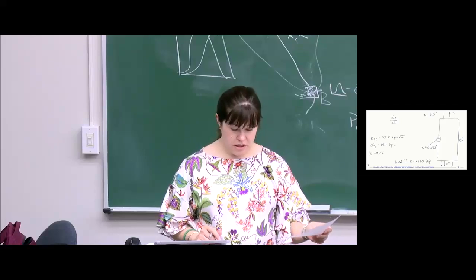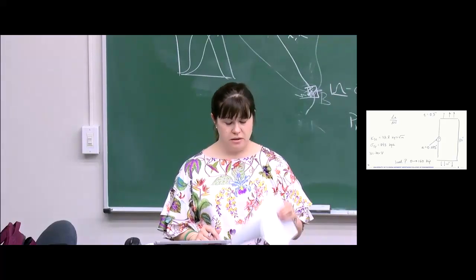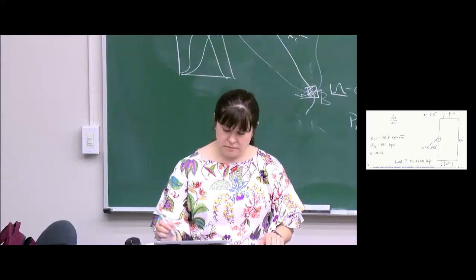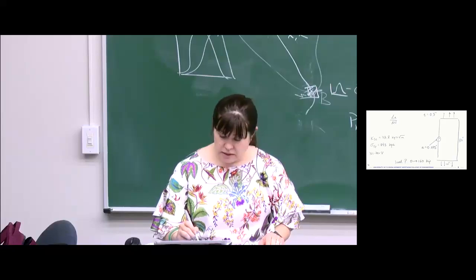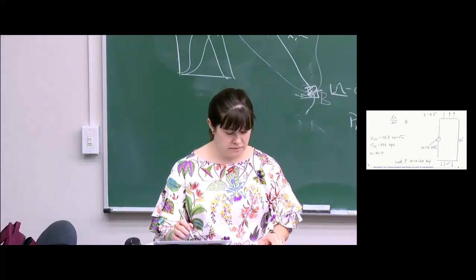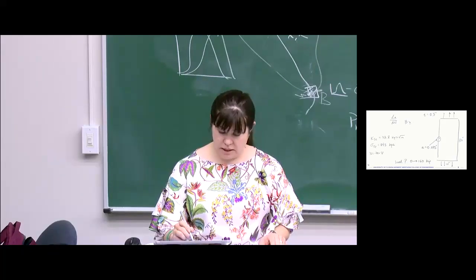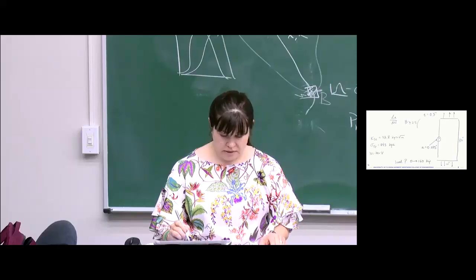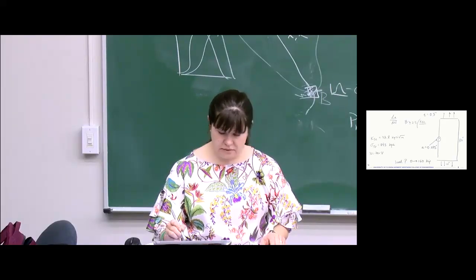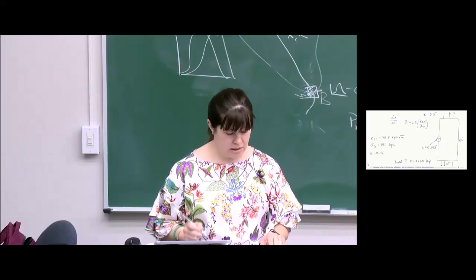And so the first thing we're going to do is just double check that this thing meets the criteria for a thick specimen that we can use plane strain assumptions. So we had this criterion that said the thickness of the plate, B, and in our case we'll check the 0.5 inches, has to be greater than or equal to 2.5 times the plane strain fracture toughness K1C divided by the yield point, and that has a square on that term.